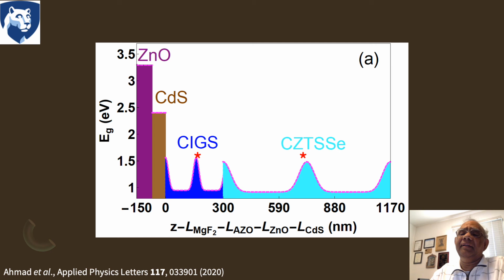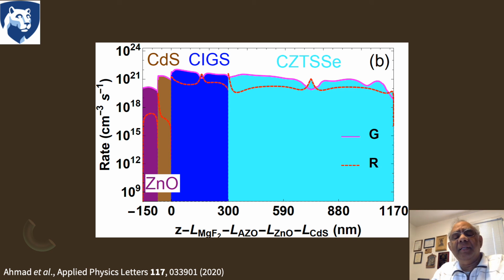The optimal bandgap grading also consists of a triangular region in the middle of each absorber layer. You can see them marked by stars, red stars. This middle region creates a high drift field that favors charge carrier collection deep inside the absorber layer. In at least half of each absorber layer, the band gap is uniform and low. This is good because then less energy is needed to excite an electron-hole pair across a band gap. This figure shows that, generally speaking, the electron-hole pair generation rate is higher than the recombination rate throughout the two absorber layers.